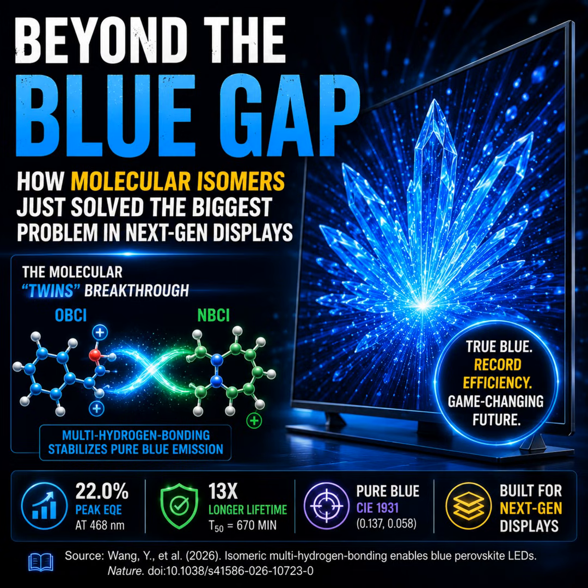Wow. So they solve the insulation problem that the quantum dot method suffered from without having to actually shrink the crystal. And it solves the exploding engine problem, too, because that network of hydrogen bonds, that twin arm linking, locks the fragile octahedral structure in place. Yes. The ions are anchored. You can finally pump that high-voltage energy into the crystal to get your deep blue light, and the ions physically cannot migrate out of position. The structure doesn't vibrate to pieces because it is tightly bound by this invisible scaffolding.